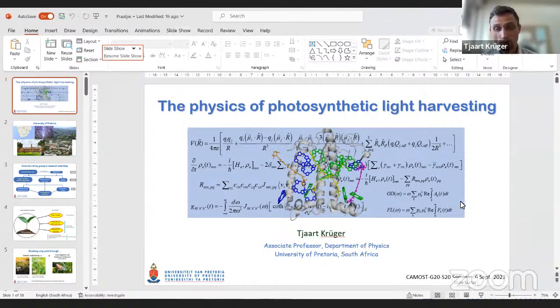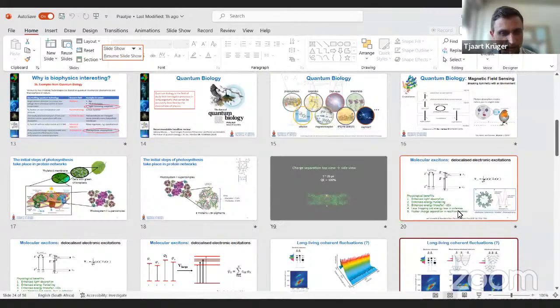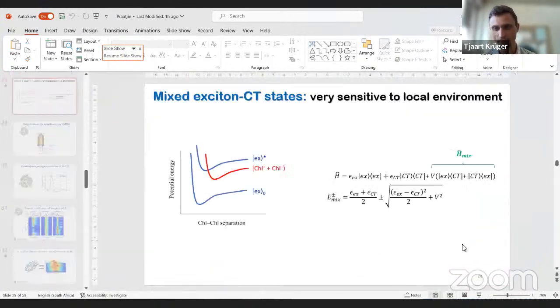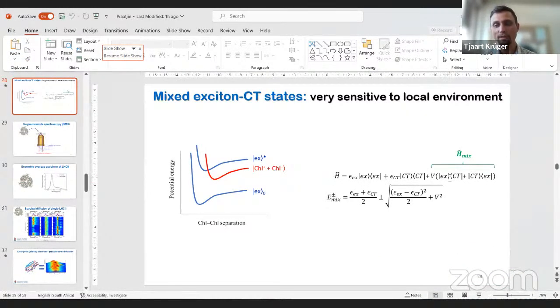So there are actually two hybrid states that form. Let me see, where are we now? This one. Okay, so you get an exciton state with some charge transfer character. So it's mainly an excitonic state, and it's mixing with a little bit of charge transfer state. So this will be the state with a high oscillator strength. So that will be the emissive state, and normally this is the state that is low enough in energy that it will be populated. This other hybrid state is normally much higher in energy than the exciton state, so that will not be populated, and that is a charge transfer state with some excitonic character, but because it's not populated, it is actually not relevant.